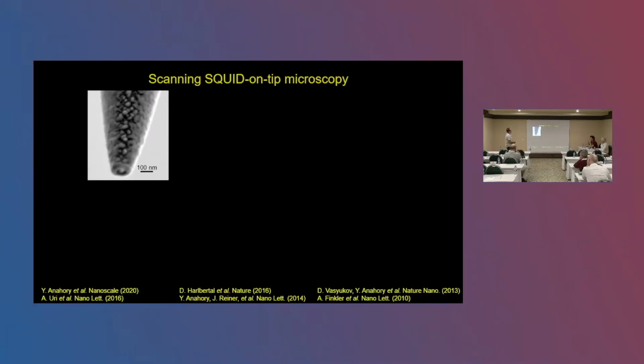So the scanning SQUID-on-tip microscopy is a microscopy technique that allows magnetic and thermal imaging at the nanoscale. This is an SEM picture of one of our devices, a relatively big one, with an outer diameter of about 160 nanometers. It's built on a quartz pipette, or a glass pipette, and there are two lead leads here that are superconducting, separated here by a non-percolating gap. The idea is that these two lead leads meet at the end of the pipette where the SQUID loop is formed. That allows us to have a SQUID that we can bring in very close proximity to the sample. And we can make them relatively small, below even 40 nanometers.